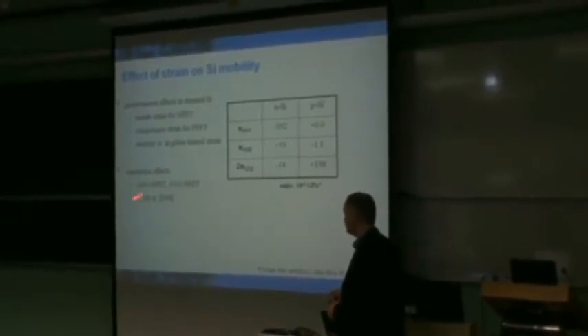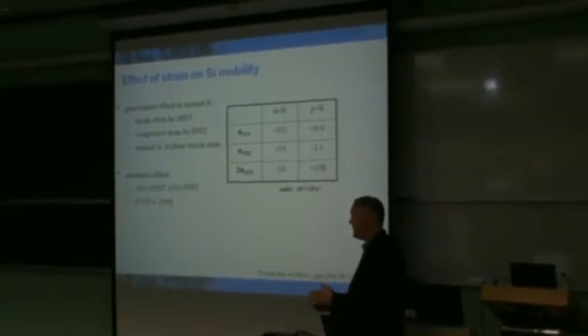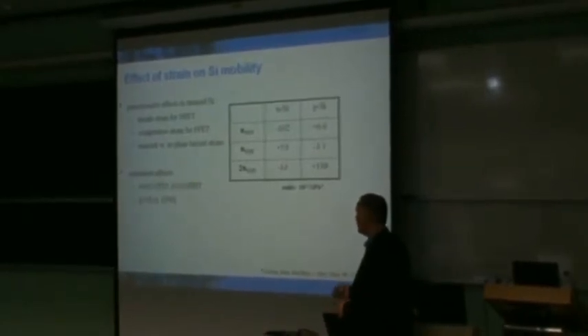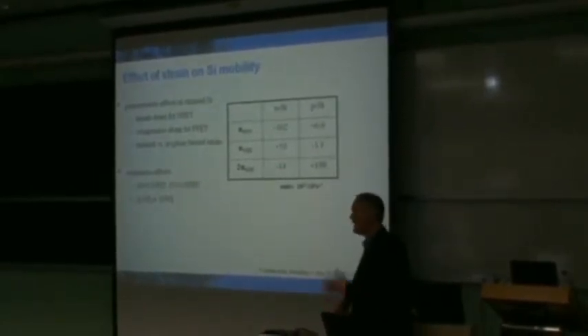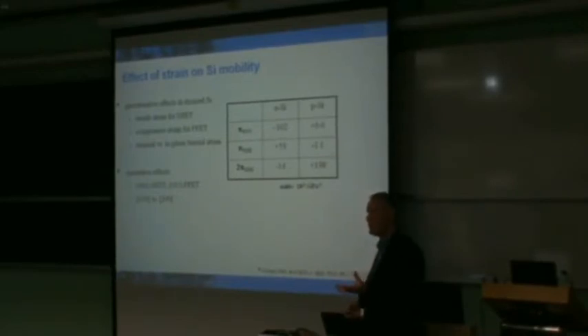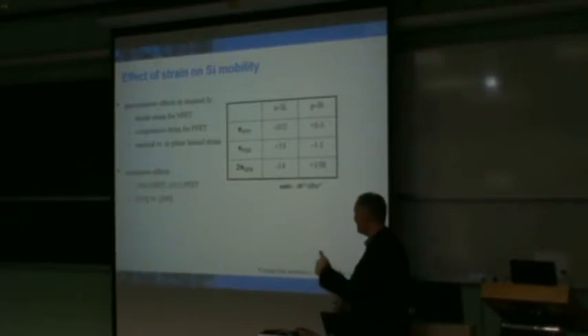Nevertheless, there are schemes that look at not only different orientations, but what's called here a hybrid orientation, where on the same substrate, you can actually try to grow different orientations. So this refers to the out-of-plane direction, basically. In one case you'll have an 001, aligned with the cube, and then one that is at 45 degrees to that cube.